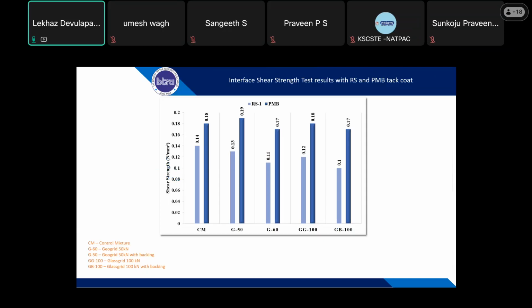So you can see almost all the geogrids have a similar interface friction or interface shear strength. So we confirmed that no delamination is happening for this. And the tack coat dosage which we followed, 0.4 to 0.5 kg per meter square, was okay. We got a lesser result for 0.2, which is our usual standard practice as per MORTH.